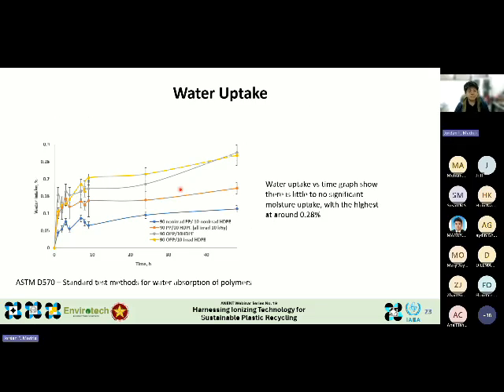Aside from density measurements, we also evaluated the water uptake of the samples after a 48-hour period. The results showed minimal water absorption across all the specimens we tested. This is a very encouraging finding, especially because we are aiming to apply these products in building and construction materials, where resistance to moisture is critical for durability and long-term performance.